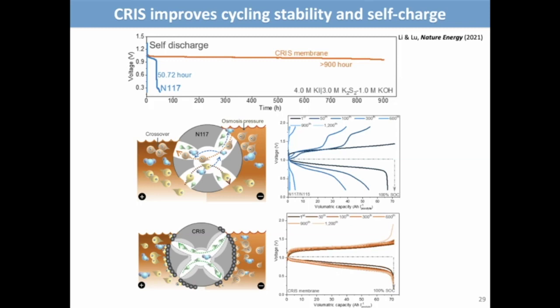To show its efficacy, we first check the self-discharge. We charge the battery to a full charge state, and then let it sit without charging or discharging and measure the OCV. You can see that with the commercial membrane, the self-discharge is very quick and the battery basically goes from full charge to almost 0 volts across 50 hours. But with the modified membrane, it can last for more than 900 hours with very small decay over the course of 900 hours.